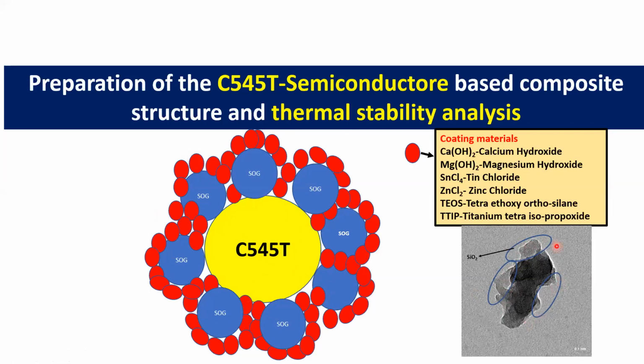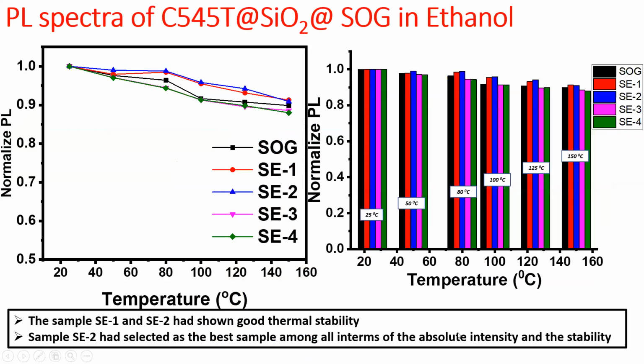We see that the SiO2 coating, although it is not uniform because the particle structure itself is not uniform, since C545T does not have a particular structure, is still a good coating. It took 6 months of effort, but I got a good coating of silica. So it is anti-reflection, and it is also moisture resistant and thermostable because SiO2 is all around it. This is industrial work, and I am expecting a patent from this.